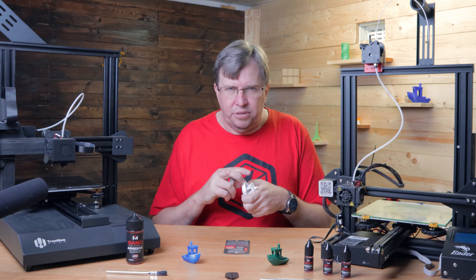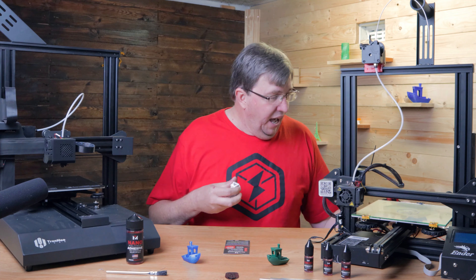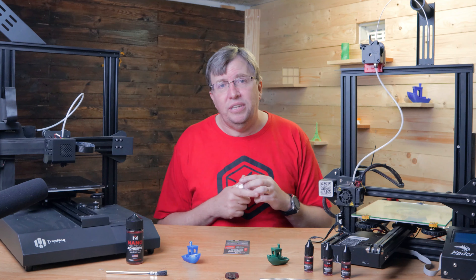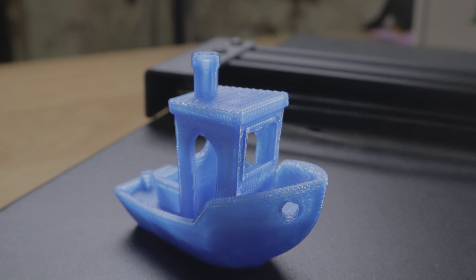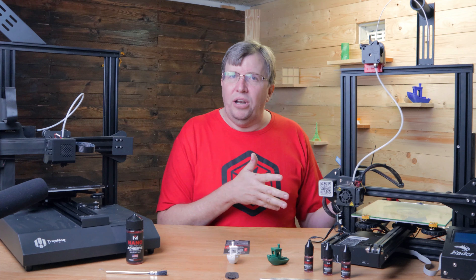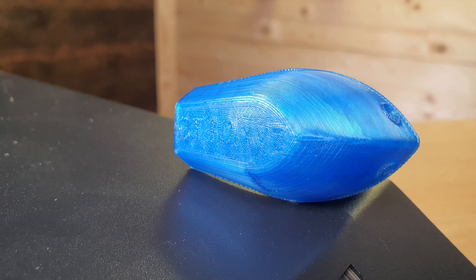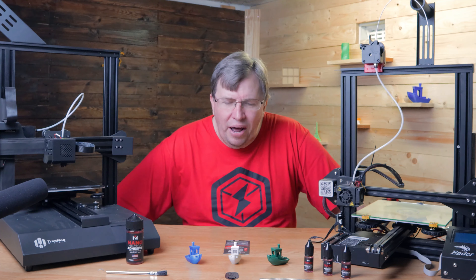The acetone vapor smoothing definitely came out nice - it is something to play with. I did get acetone on the bottom of the print which ruined the bottom a little bit, but it is amazing how smooth it came out. I'll do a video in future about acetone vapor smoothing. Here is another ABS print on the glass - the bottom looks absolutely stunning, but I had a bit of layer adhesion problems due to the filament being a little bit moist. I'm using eSUN ABS and it's about a year old with some moisture creeping in.